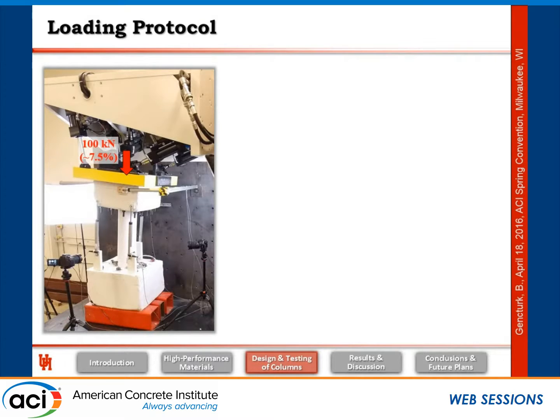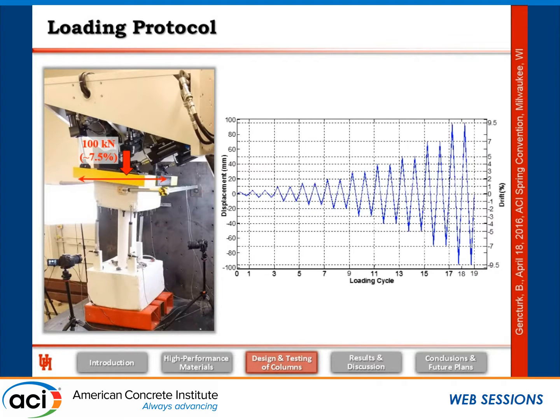And in this test, we used about 22.5 kips of axial loading, which corresponds to 100 kilonewtons. And this corresponds to 7.5% of the gross axial capacity of the columns. And this was our lateral loading protocol. We started, I think, about 0.5% or 0.25% drift. And then we applied 2 cycles at each drift level, and we went all the way up to 10%.